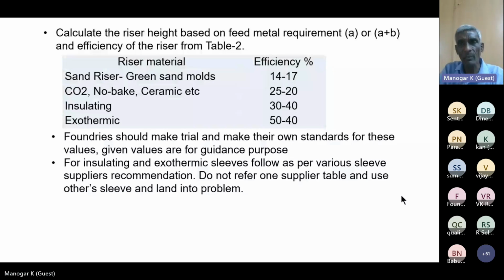Calculate the riser height based on the feed metal requirement. We have already arrived at the riser diameter and we know the weight we need. So we have to find out the height from the weight we need from the riser. The riser efficiency should be considered. For that, consider what riser you are using, either a sand riser, insulating riser or exothermic riser. Its efficiency is given by the suppliers. So take care of that efficiency and calculate the riser weight you want. The foundry should make trials and set their own standards to confirm the efficiency.